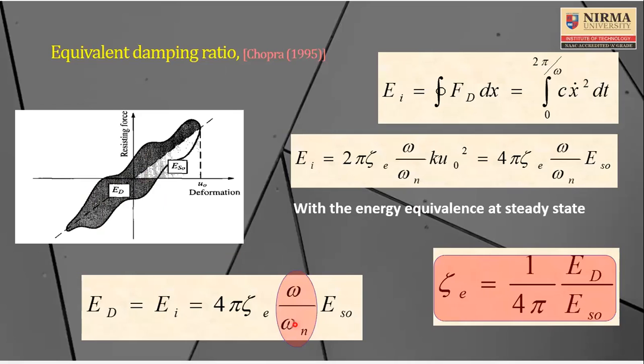Of course, many researchers have their own reservation as far as using this omega by omega n. Various literature and research has been carried out, including by my own student, and we figured out that this assumption prevails because up to certain values of frequency ratio, there is not much difference in the energy loss, and therefore you can very well consider that the hysteresis loop can be equated with an elliptical loop of a viscous damping at a resonating frequency.